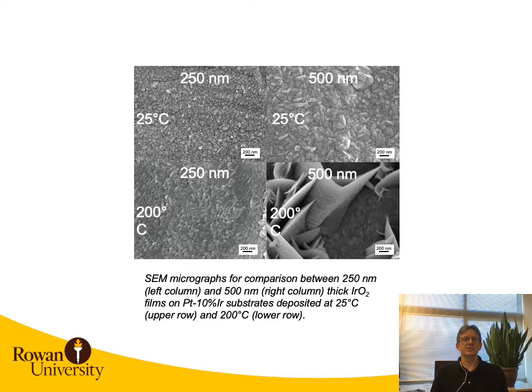This slide shows differences in microstructure based on thicknesses. So at 25 degrees, this upper panel here, you see the 250 nanometer thickness versus the 500 nanometer thickness. So more spherical grains to more elongated grains. Then at 200 degrees, we see that the grain sizes are a little bit larger here at the 250 nanometer thickness. But when we go to the 500 nanometer thickness, we see a lot of these surface structures, these platelets on the surface.